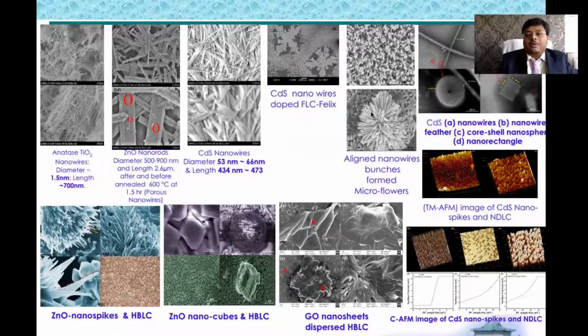And then a bunch of nanowires accumulated and aligned as a microflower-like structure. And you can see here the nanocubes and nanospikes, zinc oxide, and this is a hydrogen bonded liquid crystal, a worm-like structure you can see here on these two sides. And this is our graphene oxide nanosheets. When it is dispersed with the liquid crystal, a nanofiber type attachment is obtained, the same morphology, as we confirmed.